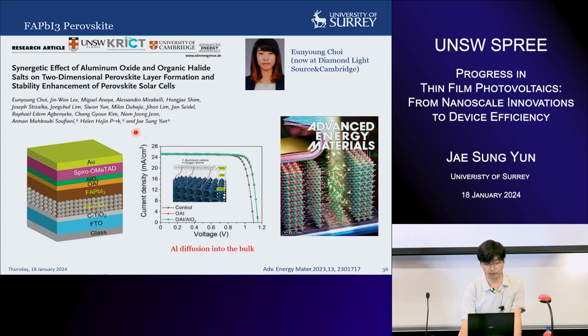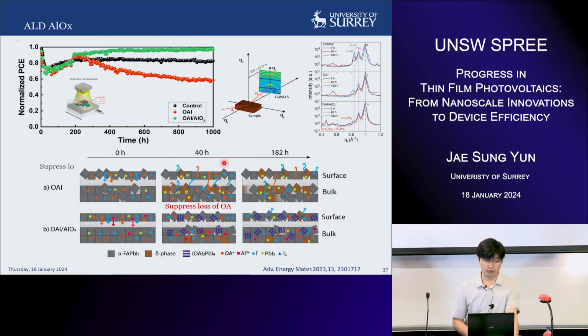And this is known to be effective especially for stability reasons. What we found is that when you have aluminum oxide on your film, and if you anneal this film or if you illuminate it with light, your aluminum actually will diffuse into your perovskites. And what we found is that once aluminum diffuses into your material, it actually heals, cures the defects in the bulk. And it is also going to improve the stability quite a lot.